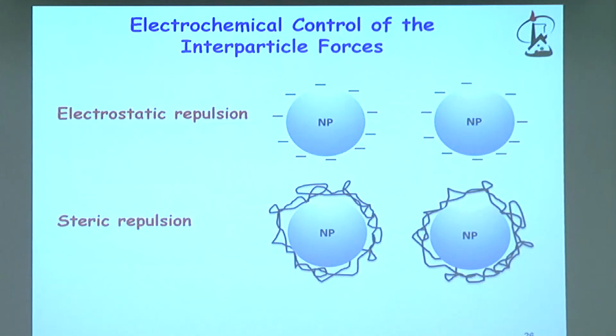So if you know the nanomaterials, when they are dispersed in solution, they tend to spontaneously aggregate. And the reason for that is that as you make the material smaller, because of also the curvature and so on, their surface energy actually increases, which means that if you have nanomaterials in solution, they will spontaneously aggregate. And this requires actually to stabilize them and to introduce some kind of a repulsion between the nanoparticles in order to prevent this spontaneous aggregation.